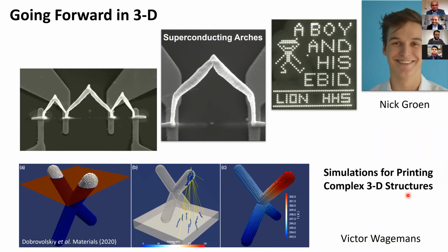Please. Yes, okay. So my question is about the width of this wire, the superconducting wire that you used. What minimum could you achieve? Because if I'm not wrong, this coherence length of tungsten carbide should not be more than 5 nanometers. It should be around about that, isn't it? No, but the coherence length is about 6 nanometers, which, by the way, is a very important point.